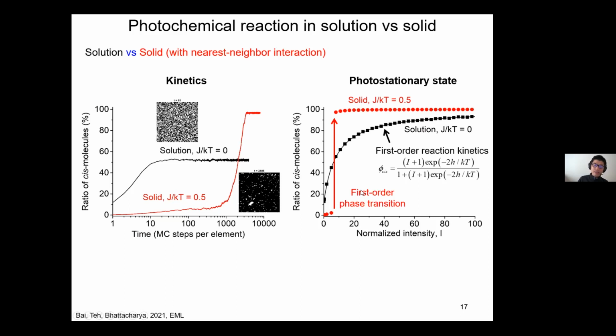Well, in solid, you do see a first order phase transition. There's a jump or discontinuity of the order parameter here, which is the cis ratio. So initially, neighbors like neighbors, so they don't want to flip. They either flip all or they don't flip, right? So this is the idea.